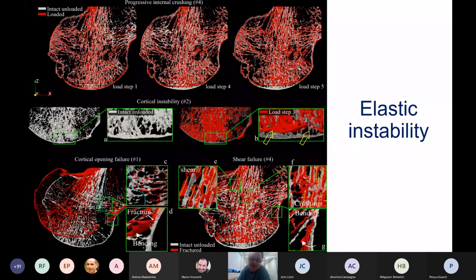So does that apply to the fracture region and fracture behavior? In the last line, we see two representative cases: one for cortical opening, and the other the shear failure case. What we see on the bottom right is bending of the cortex in the very proximity of the region, and throughout the fracture line, we do not see a significant permanent deformation across the whole fracture line.